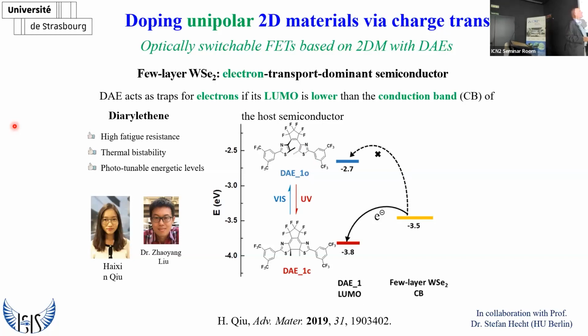different energy levels. And actually, the idea is we use tungsten diselenide. This was the PhD thesis of Haixin Qiu. In the first part of this story, we use tungsten diselenide with a thickness such that it was acting as a dominant electron transport semiconductor, because depending on the thickness, tungsten diselenide can be n-type or can be ambipolar. We use diarylethene because it has high fatigue resistance, thermal stability, and a phototunable energy level.